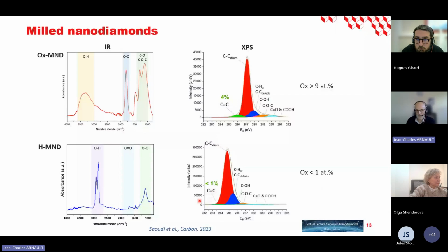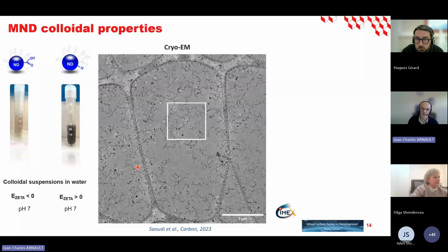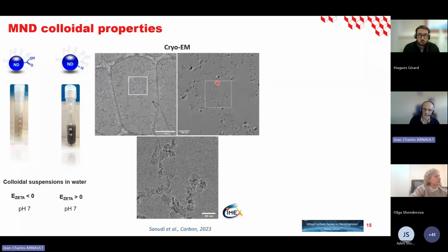So looking now at the colloidal properties of such milled nanodiamonds, you can also, with these particles, obtain the zeta potential I mentioned before for the detonation particles. But we looked more closely at the spatial distribution of the particles in the water using cryomicroscopy. So this is a large-scale image. And you can see, and this is something very interesting, that these particles are forming chains, but over micron-size chains. If we look inside more closely, we can see that these chains are formed by facet-facet interaction. So this is something very interesting and specific to hydrogenated milled nanodiamonds.